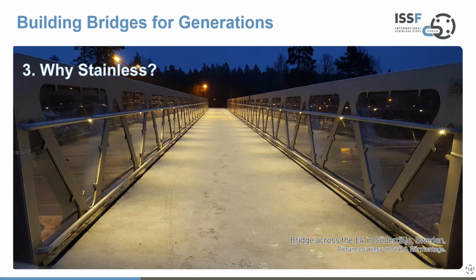And the question should be, what temperature would you like it to withstand, I think. Because there are so many stainless steels, it's a question of determining the operating environment, and we will identify the steel. Well, let's just take as an example duplex stainless steels, because we're talking about duplex for bridges. And the normal working range for duplex stainless steels without creating any problems is -50 centigrade up to 300 degrees, maybe 350 degrees centigrade.